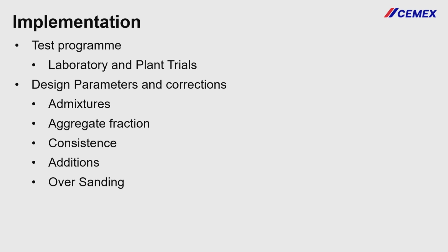Does a PC admixture give the same water reduction in a CEM2AL or a C2C-SL plus SR as it does to a CEM1 and a C3A plus SR? We need to look at the aggregate fraction. Is our percentage fines going to be the same because I've got a more cohesive cement? So actually I can take some sand out, possibly. I need to look at consistence. Does it need the same amount of water to give me an S1 or an S4 slump? What about additions? Do I use the same percentage of GGBS to give me the same compressive strength performance? Because again, one of the focus areas as technologists is wastage, excess of design.